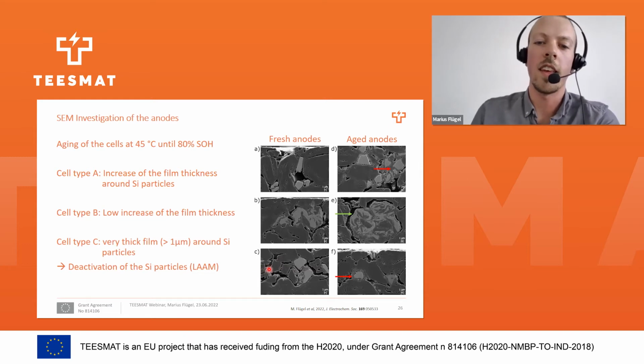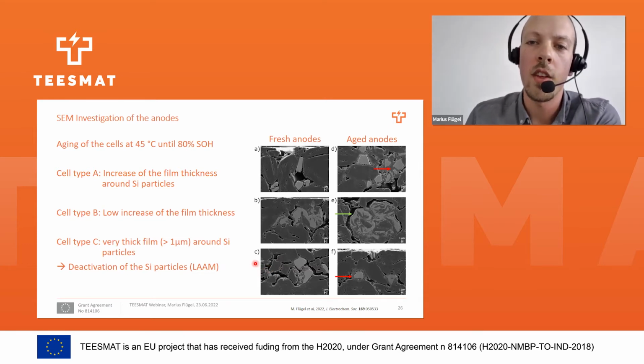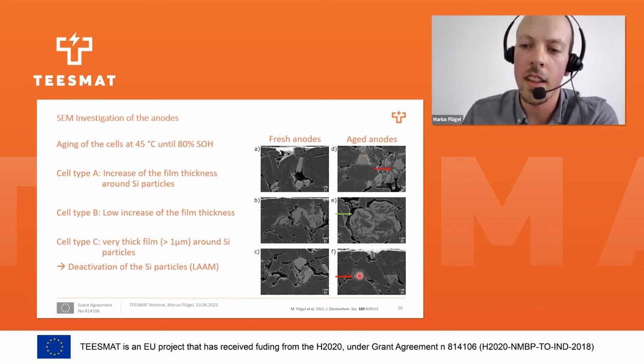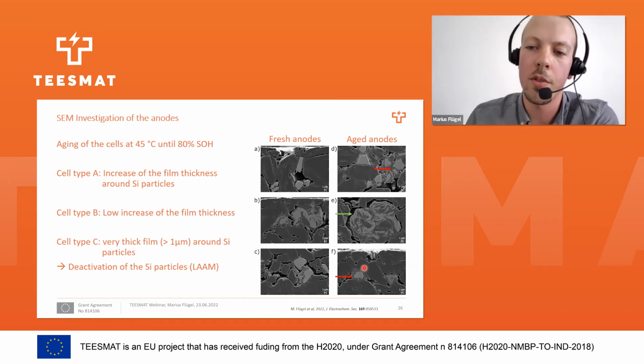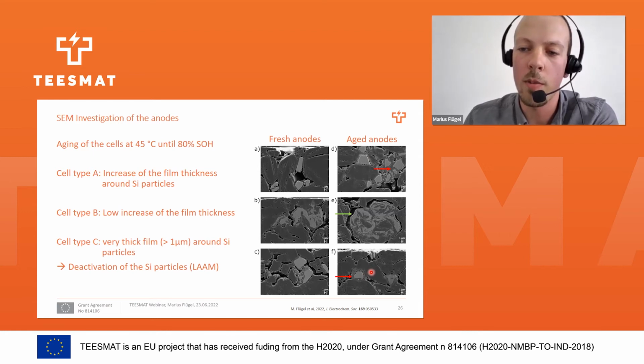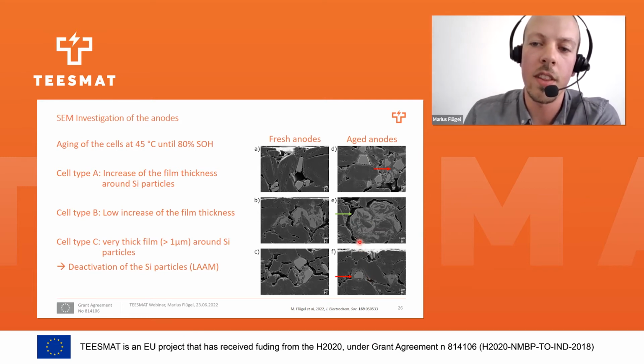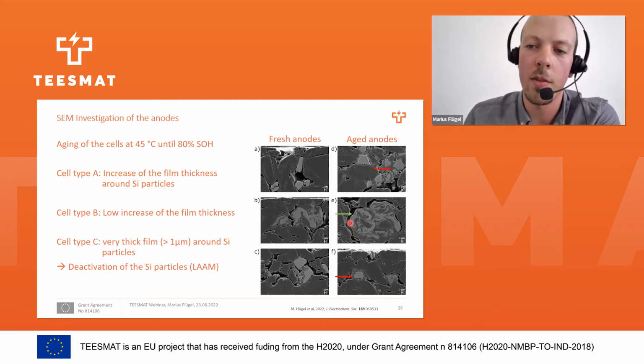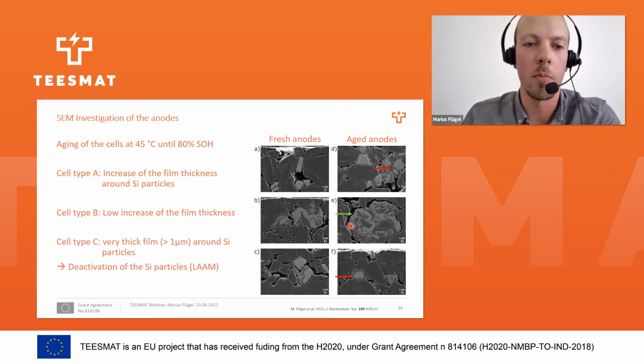With SEM, we got similar results. The fresh cells can be seen in the left column. And after aging, we saw heavy film formation around the silicon particles for cell type A and cell type C. For those particles, the lithium has to diffuse through more than 1 micrometer of film to get to the silicon. For cell type B, where we didn't see any loss of active material, there is a very small film around the silicon particles.